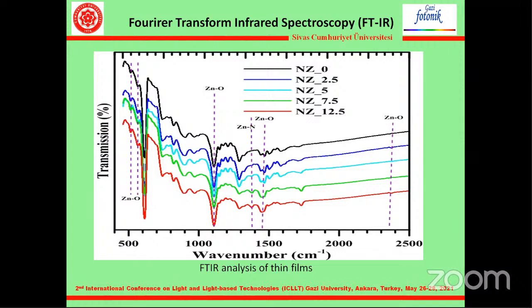1,381 per centimeter. This peak is estimated to be the zinc-nitrogen bond. This situation is also supported in the literature. As can be seen from the Fourier transform infrared spectrum results, it has been proven that the materials produced are nitrogen-doped zinc oxide.